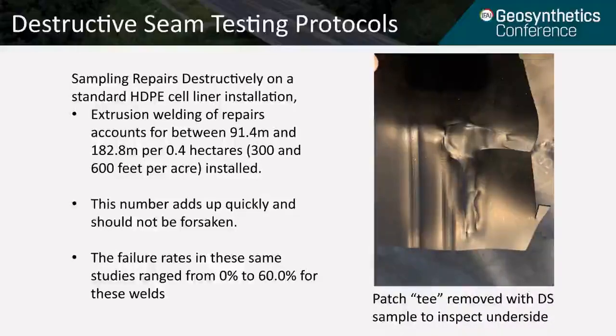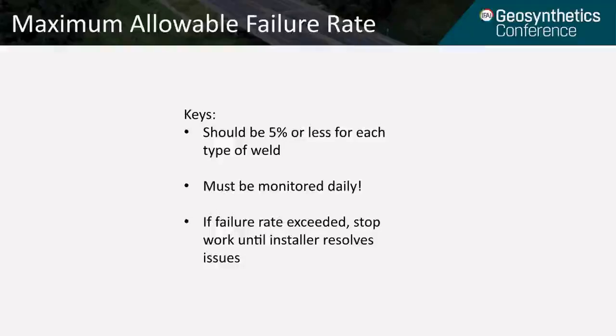The amount of inferior footage adds up quickly on projects. And for example, the Zero Leak Palo Verde project I was involved with would not have been zero leaks if we did not do destructive testing on the extrusion welds. The owner should specify a reasonable expectation for maximum failure welds of destructive samples. They should be monitored daily, and if the failure rates are exceeded, the installer should stop and not do any more production welding until they can figure out the source of the problem.